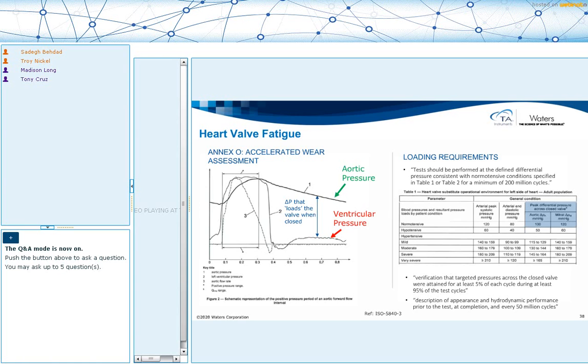So this is the wear testing or fatigue testing. And every 50 million cycles, you have to stop the test, check out your valve to measure the hydrodynamic aspect of it. So you're looking at the appearance and you're looking at its leakage to see if it is affected after being exposed to fatigue.